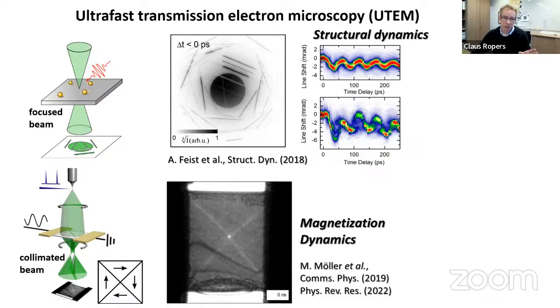Here, synchronized in a way to record a stroboscopic image of the magnetization dynamics driven by this radio frequency current. So it's this gyrotropic oscillation in this particular case of a vortex core in this permalloy thin film driven at a resonance. And as you can see, basically also here with picosecond resolution,